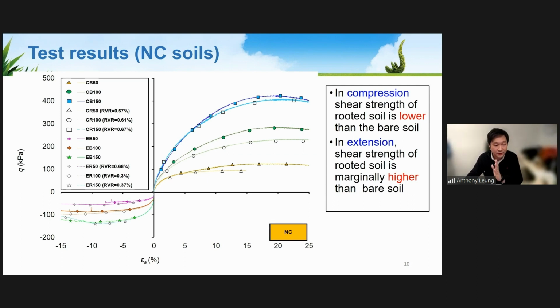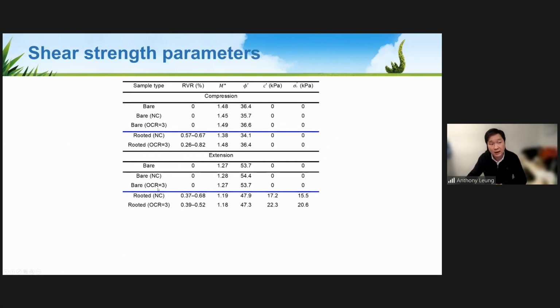One thing, sorry, I forgot to mention is the species we have been using is the vetiver species, which is a deep-rooted species, whose roots mainly grow vertically, just like one of the pictures I showed you earlier. They like to grow vertically rather than laterally. So that also is very important information when we study the anisotropy, because the root orientation has an effect on the orientation of the major principal stress that affects the anisotropy. So we observed quite interesting results. If you look further at the shear strength parameters, which means the friction angle and cohesion.